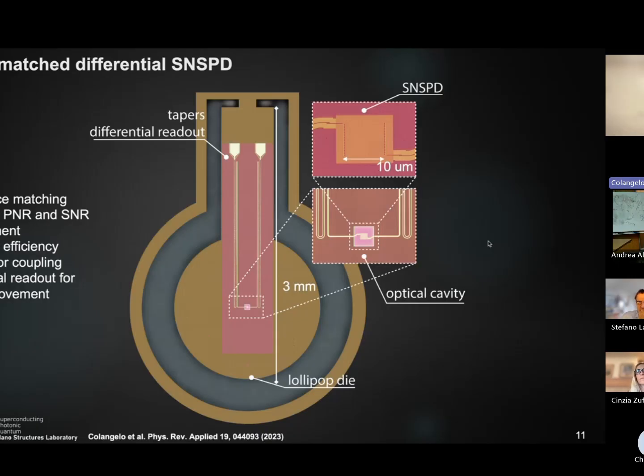And second is the fabrication, because each of those nanowires is 40 nanometers. So it's actually very challenging to fabricate. And we're trying to do it. It seems that we are getting there. And we are, again, trying to match and integrate the plasmonics with the superconductivity and trying to get an even better detector for mid-infrared application, both in the quantum information, but also potentially for space and exoplanet spectroscopy and all the devices that can help these disciplines.